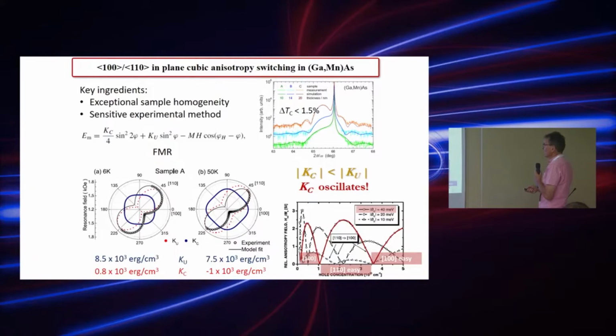So as you see, someone really has to believe that the fitting was done okay, and that this rotation really took place. Nevertheless, one could say, yes, we see the change of the sign of the cubic anisotropy constant. Cubic anisotropy indeed oscillates, so somehow this prediction has been confirmed, and to a large extent I could stop my presentation here because it looks like the job is done.